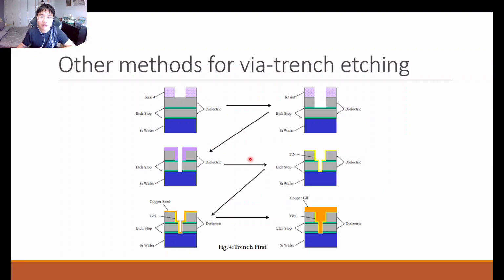However, there's a problem with this trench first etching, and that is that you see your photoresist here has a non-uniform thickness. But remember, when you learned in the photolithography topic, that your photolithography exposure machine has a certain depth of focus, a certain depth of field. So if your depth of focus is very small, and your resist in this case now has large thickness non-uniformities, it will result in poor resolution of pattern definition in your photoresist. So that is a big problem for the trench first method, and that is one of the problems of this method.